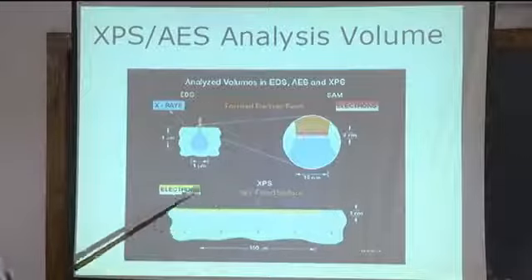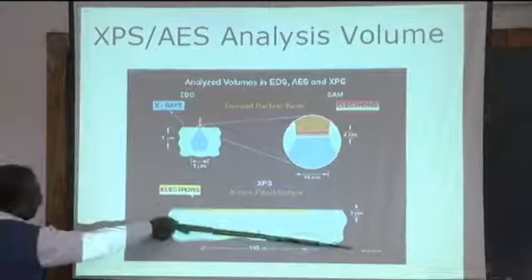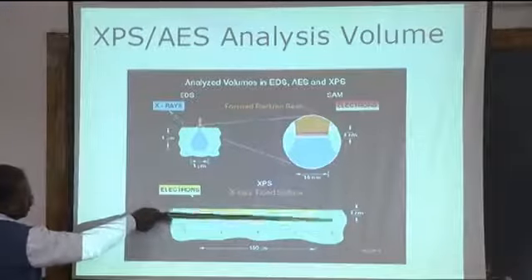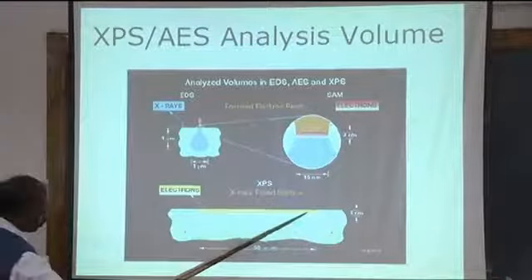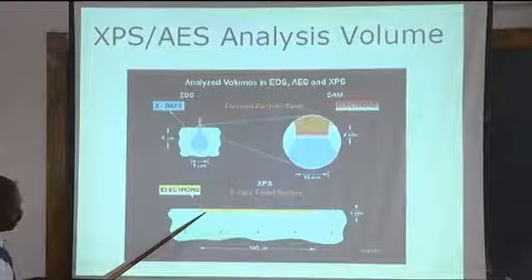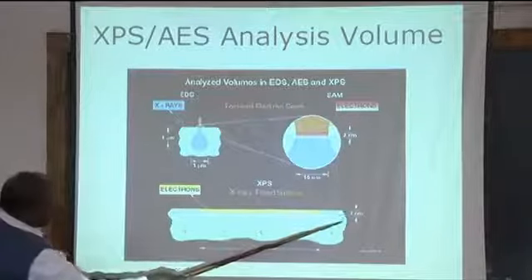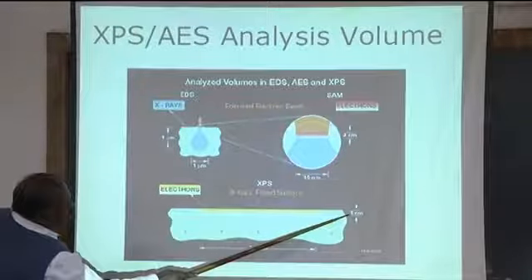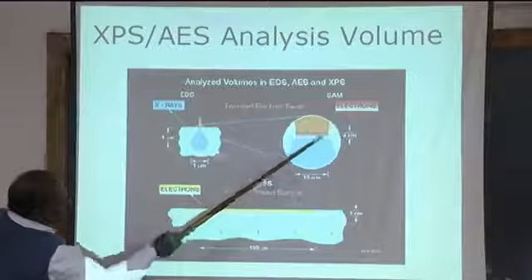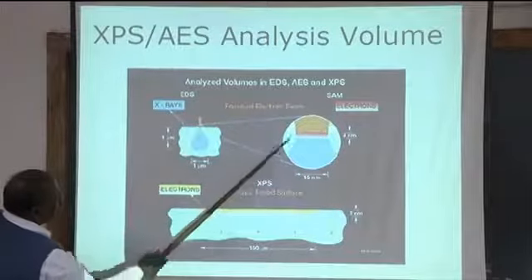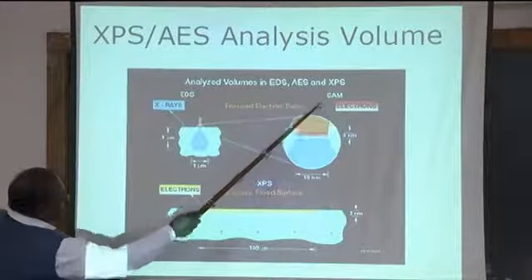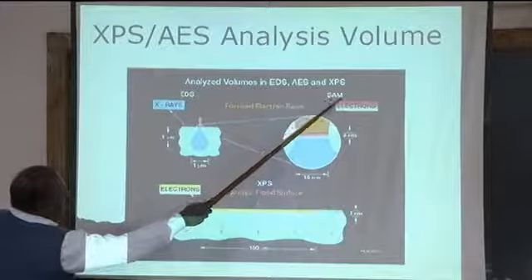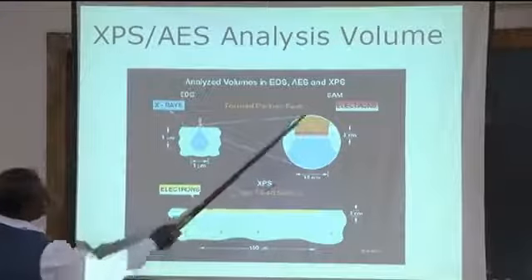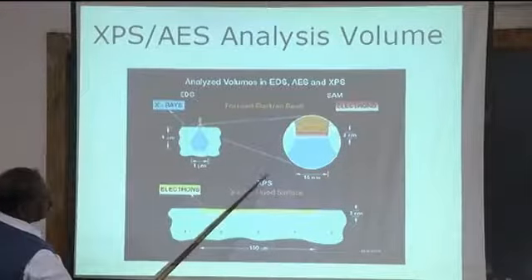Now about XPS. In XPS, the whole area is irradiated. The whole thing is giving signals, and this yellow, what is shown, is what is contributing to your spectra. What is that depth? That depth is shown here in nanometers. And this is the depth for AES. Again, AES is coming from here. What is that depth? This is the depth. That is what is used in scanning Auger microscopy. So that is where these two techniques become surface analysis techniques, and this is to differentiate from the bulk.